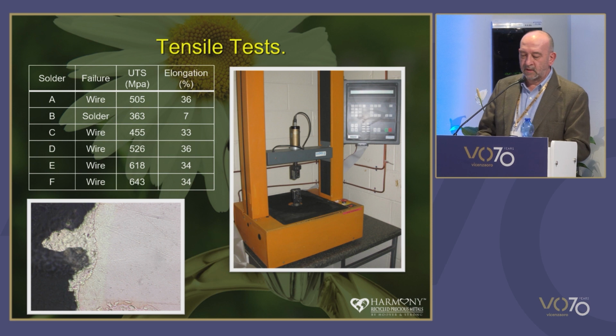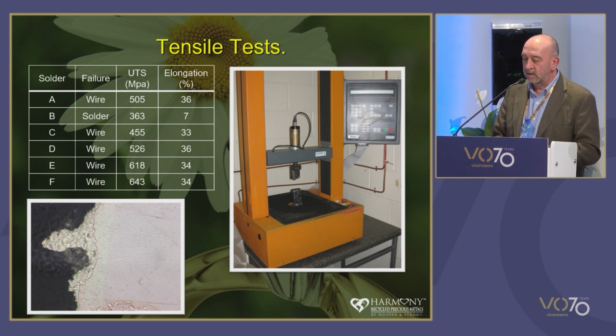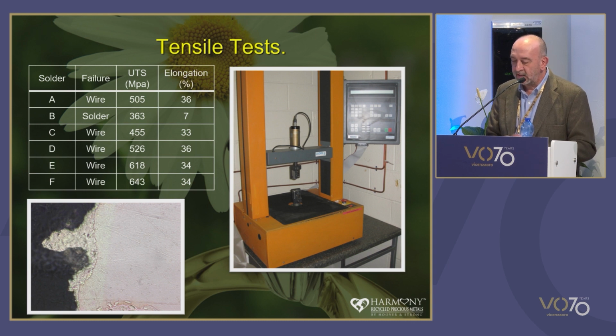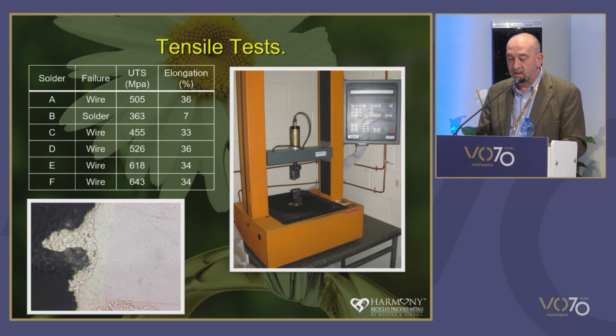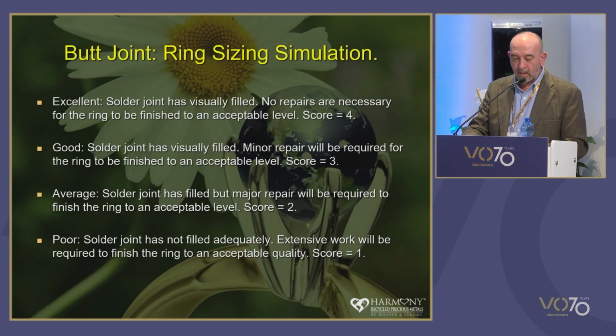For the furnace tests, the solder pieces were tack welded onto the rings to keep them in position. They were then placed on jigs and put through the furnace, and the furnace temperature was set to about 30 degrees C above the liquidus of the solder. And we evaluated the samples in the following way.